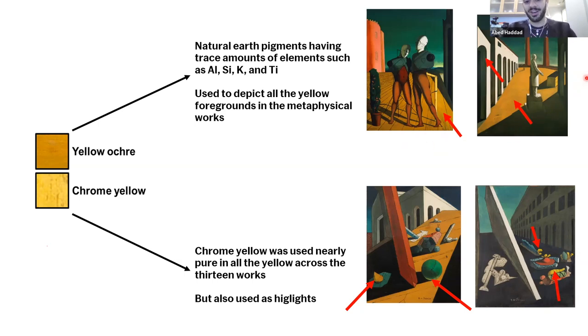It was mixed with other colors, notably other earth pigments like browns, to tone grays and shadows like the ones created by arches here in the Enigma of a Day. Chrome yellow, on the other hand, was used nearly pure in all of the yellow toys and tchotchkes across the 13 works, such as the Evil Genius right here, or toys. You can see here, it's very bright chrome yellow. De Chirico also accentuated other colors with chrome yellow quite liberally, like the ball here in Evil Genius. You can see there's a little sliver of yellow, and that was done in chrome yellow as well.